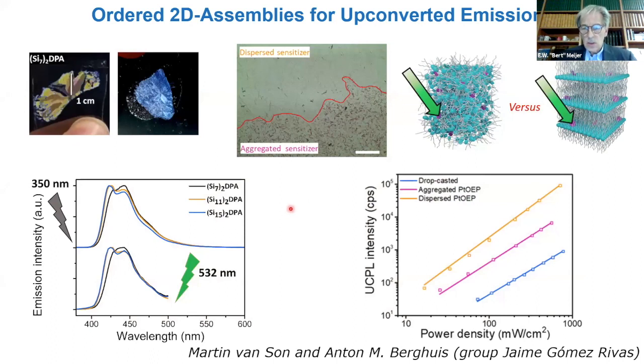And here you see some of the results. If you have it amorphous, you get that upconversion light, but it's very low. If you have it ordered, it's much higher. You can see that over here on the left side, if we irradiate at 350, we get this normal fluorescence, but now we do 532, you get the same fluorescence. And this is that upconverted light, which is low energy in, and you get higher energy out.